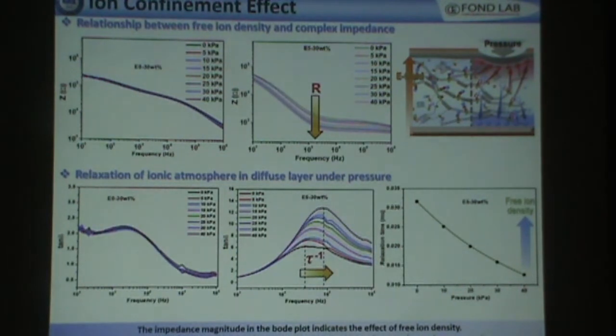So to actually analyze the ion confinement effect in our system, we also did a stress relaxation test on our samples. So here we have a sample without any chlorine functional group, and a sample with 58% chlorine functional group. We can see that even as the pressure increases, there isn't any effective change in the sample without any chlorine functional group. However, you can see that the bulk resistance actually decreases as the pressure increases.